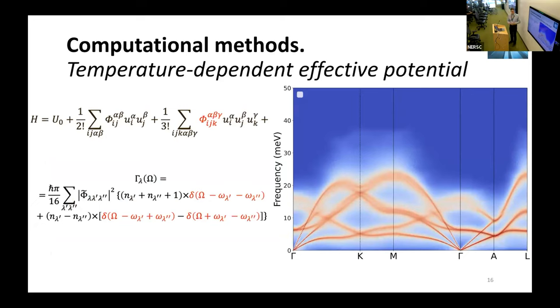What if we want to actually find out which phonon-phonon interaction contributes to the formation of this additional diffuse intensity? For this we can use the technique called temperature-dependent effective potential, which is sort of vanilla machine learning technique where we fit a third order Hamiltonian with spatial cutoff and fit the third order force constants.